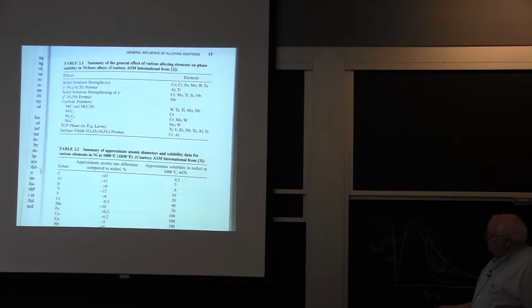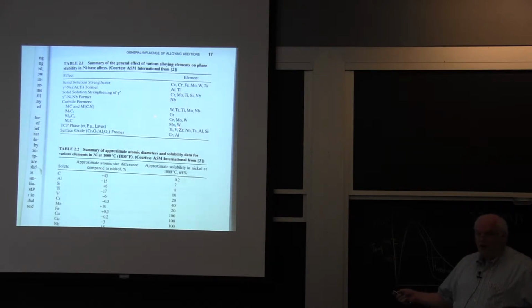And then they have what they call topologically close packed phases. It turns out they tend to be hexagonal close packed or more complex phases. Sigma, P phase, mu phase, and Laves phase, very brittle. And if you hold some of these alloys at temperature for a long period of time, you'll end up with this structure. This also happens in some of the stainless steels, and the times we're talking about are tens of thousands of hours. Okay,